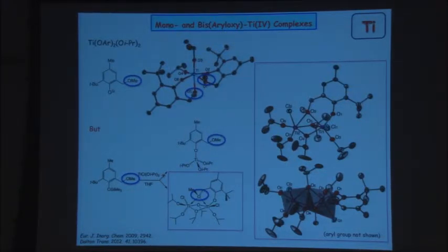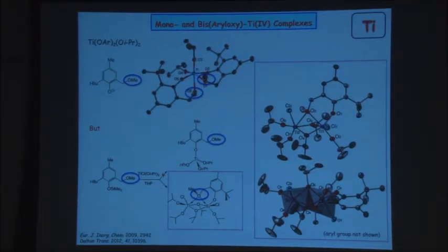But now if we compare the chemistry with this precursor and with the silyloxy derivative, instead of having the negative charge, I have a trimethylsilyl group, which is a good leaving group. You would expect basically the same thing, but it doesn't happen the same way. What happens here is that we don't form a mononuclear system, tetrahedral as before, but we form again a dinuclear system, where now the methoxy unit is bridging between the titanium centers, as established by X-ray diffraction.